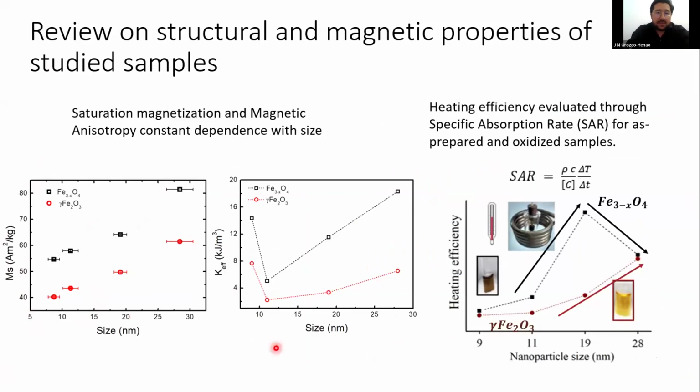As can be seen, the behavior is as expected, with saturation magnetization increasing with particle size and magnetite content. This result also reflects the interplay between the magnetite content that governs the magnetocrystalline anisotropy and the surface anisotropy, which is prominent in the case of the smaller nanoparticles.